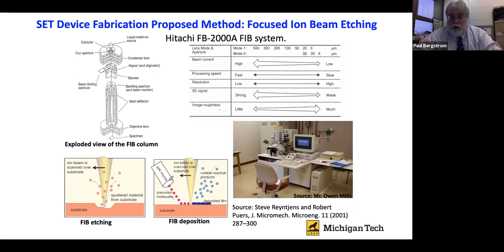So we proposed a method using focused ion beam etching as a way of producing these isolated quantum dots and the features that were required for the structure. So a focused ion beam behaves very much like a scanning electron microscope, where instead of an electron beam we're now producing a beam of energetic ions that have enough kinetic energy that they can ablate or etch materials from the substrate. Now, most of the time, this is a liquid metal source like gallium. Gallium is a very easy metal to use in a focused ion beam system, but there are sometimes other sources that are used. The other nice thing about gallium is it is heavy, and it also allows for a good etch rate of other types of materials, because it's a heavy ion.